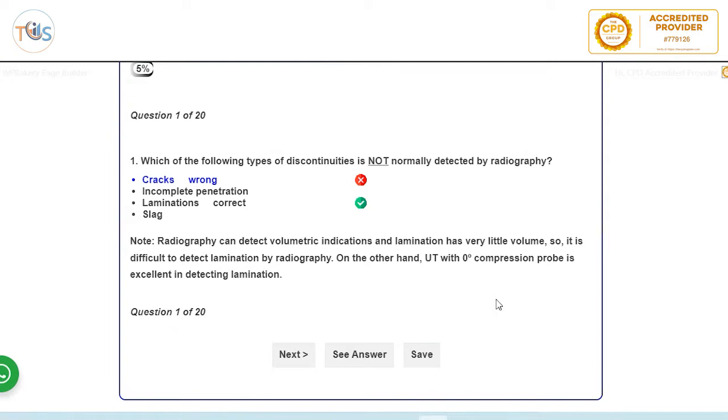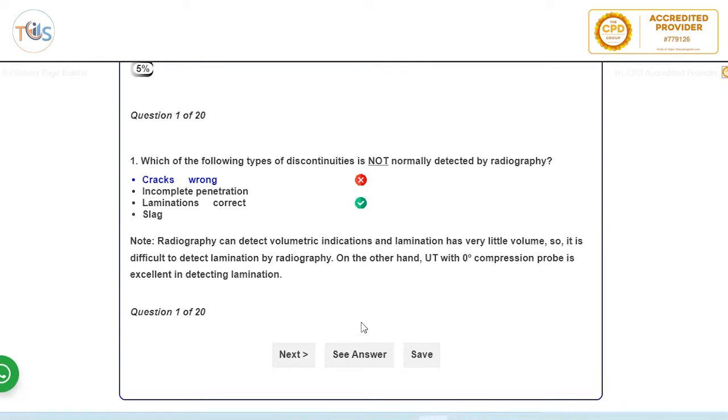Normally you see anything brighter than the surrounding area, that's a defect or indication. Now in case of lamination, there is not much space between two parts which are not fused during the pipe plate manufacturing or plate manufacturing, and hence it's very hard to see the lamination in radiography. The best NDT technique would be UT. Obviously MT, PT, and RT, and VT also you cannot see because the lamination is always inside through the thickness, inside the vessel plate.